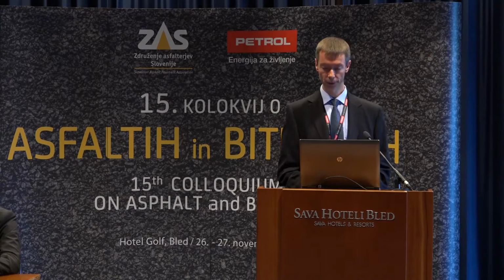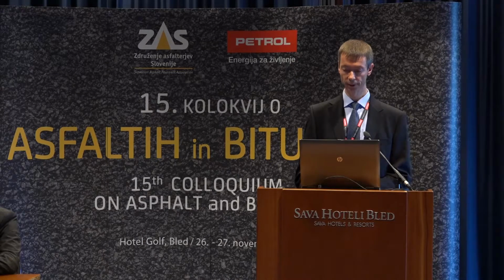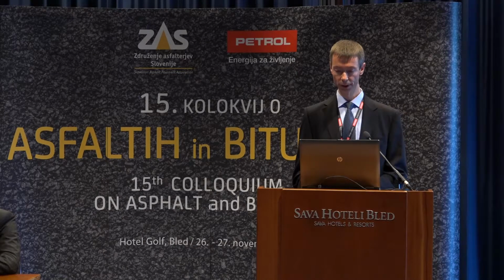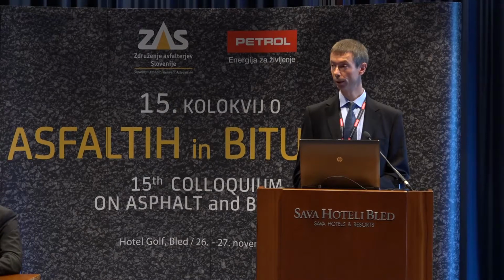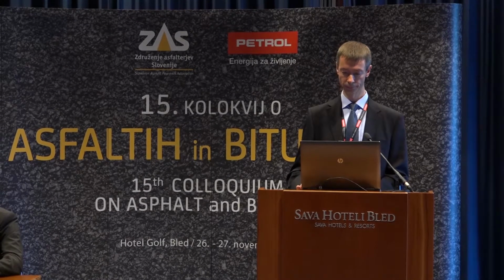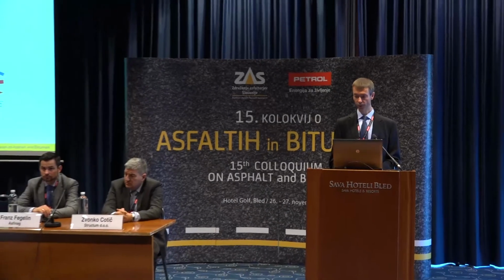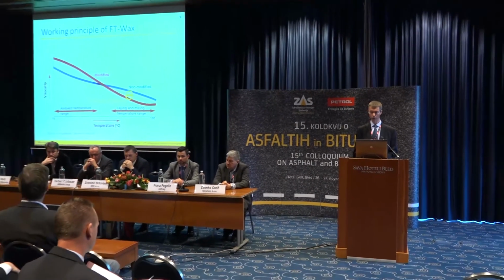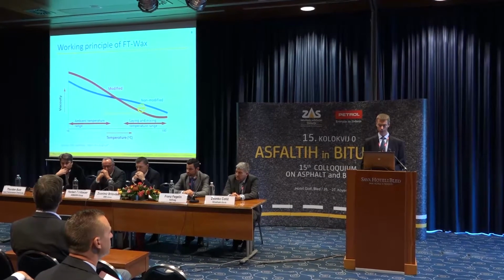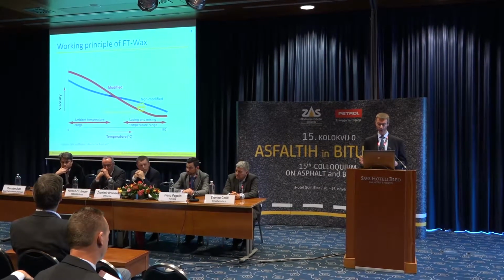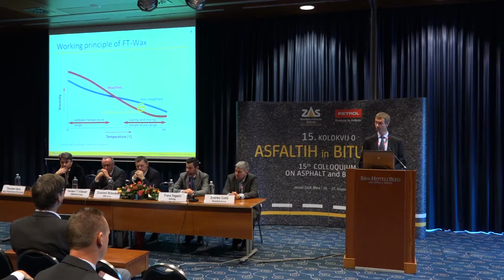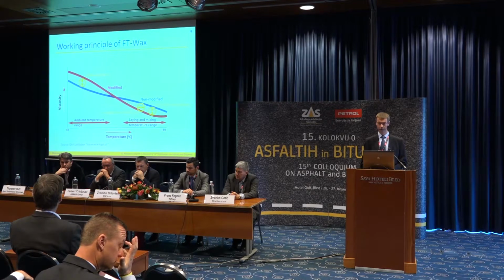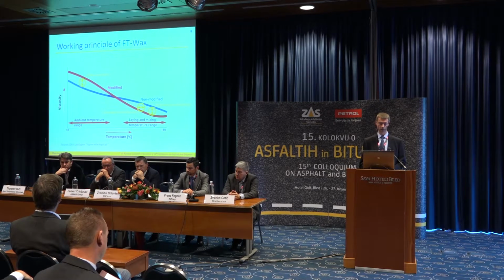At the mixing and laying temperature, the FT wax decreases the viscosity of the bitumen and therefore improves the workability of the asphalt mix. If alternatively, if we reduce the temperature, we can keep the viscosity as normal. At the surface temperature of the finished asphalt, the wax stiffens the bitumen and improves the deformation resistance of the asphalt pavement.